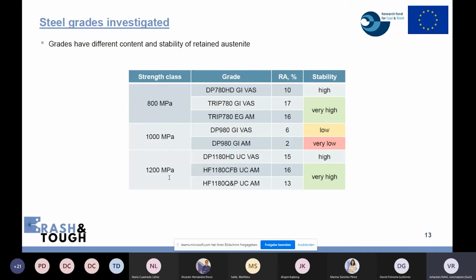Then we had a high stability of the retained austenite for the DP grade in the 800 megapascal class, and for the DP grade with low yield strength in the class 1200 megapascal. We had a quite low stability of retained austenite for the DP grade in the class 1000 megapascal, which had about 6% retained austenite, and we had a very low stability of the retained austenite for the DP grade in the class 1000 megapascal, which had hardly any content of retained austenite. So the grades had different content of retained austenite as well as different stability of the retained austenite.